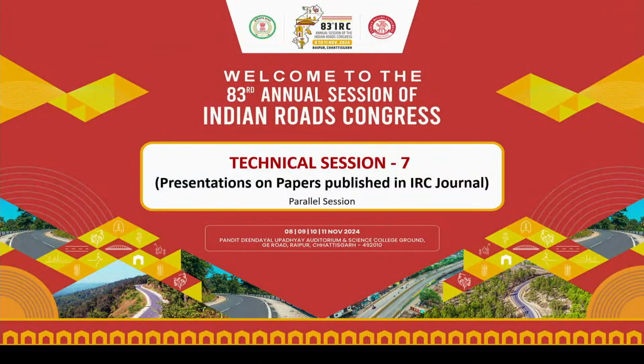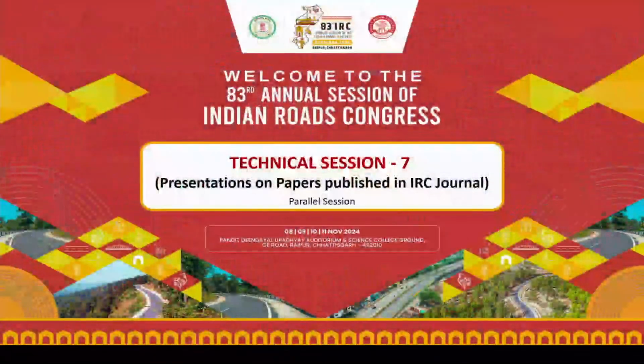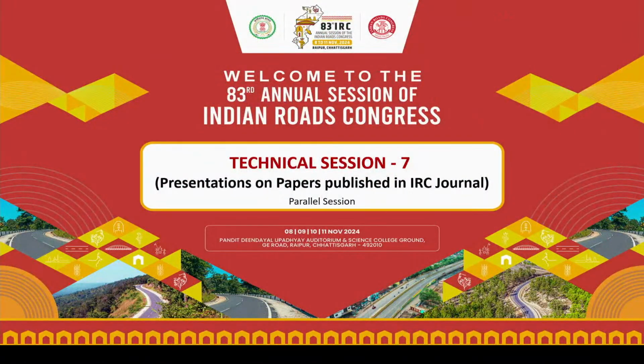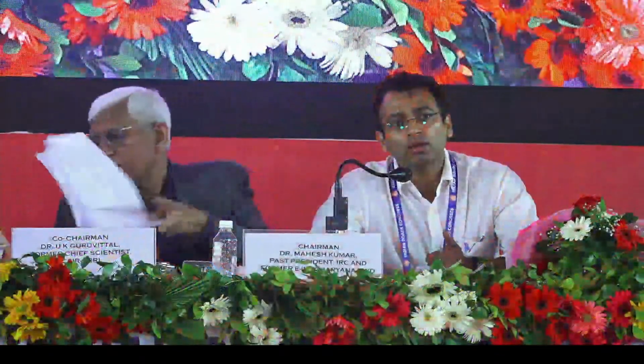Okay, I'll answer. As you know, this study was sponsored by NHAI. The idea was to see how the air voids and the volumetrics change the performance. Just after compaction, as was also indicated by Professor Raju, let us say the compaction is to a level of 92 to 94% of GMM, around 6 to 8% air voids. So we have to simulate the same at the same binder content.